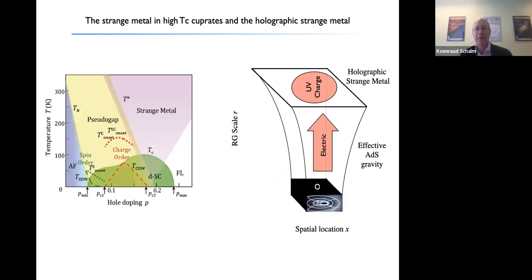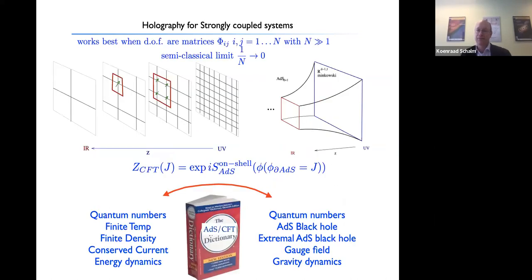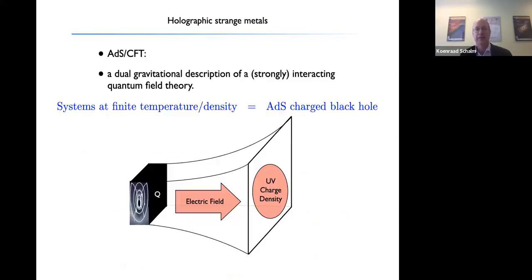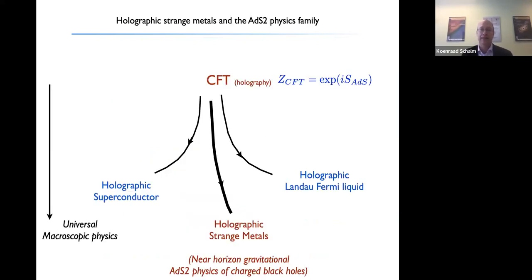So as before, we do this in a holographic metal. We model the strange metal by some electrically charged black hole in an effective AdS gravity. And we use the AdS/CFT correspondence to compute the response functions through the bulk-boundary correspondence in this system. And as almost all of you know, we're doing this at an average finite density. So we have an AdS charged black hole. And the conceit, of course, is that this allows us to get to a holographic strange metal state, which is essentially the near-horizon gravitational AdS2 physics of charged black holes. These are what strange metals are.